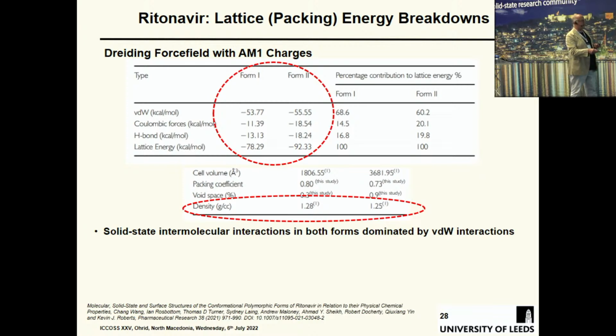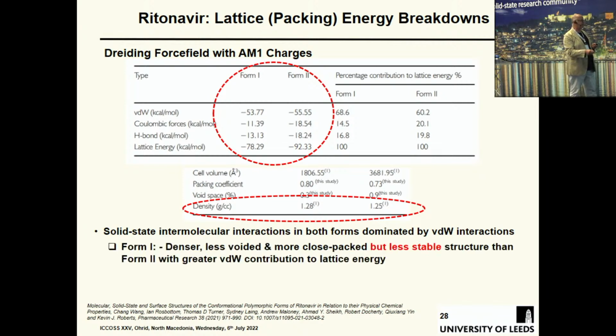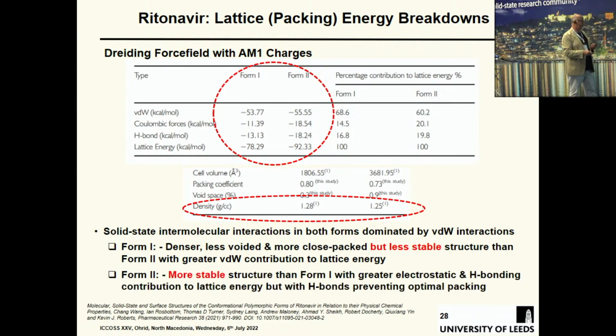And again, coming out with the density being higher in Form 1. Solid-state interactions, both of them dominated by van der Waals interactions. Form 1 is denser, less voided, more close packed, but less stable structure than Form 2, but with a greater van der Waals contribution to lattice energy. Form 2 is more stable than Form 1 with a greater electrostatic and hydrogen bond contribution to the lattice energy, but with hydrogen bonds preventing optimal close packing.